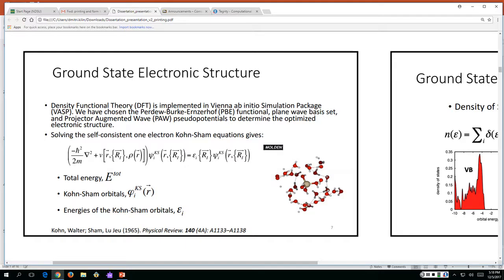And so another thing that we wanted to take a look at was during optimization of the material, if we start from this cubic structure, the cubic structure is known to be the high temperature geometry. And so during optimization, we're going to see some type of restructuring to a different geometric phase. And so the ground state distributions for the 3 different phases are shown, and then also an overlay of the calculation along the molecular dynamic trajectory to determine if the structural shape was maintained, which it was.